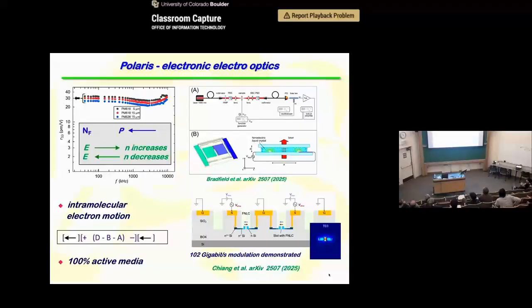So if you have a ferroelectric nematic medium that's got a polarization, then if you apply an electric field along the polarization in one direction, the refractive index of the medium will increase. And if you apply it in the opposite direction, the refractive index of the medium will decrease. And it could be one way or the other, depending, relative to the polarization. But you'll always have this refractive index that's a linear function of applied field. So you can use this to do phase modulation.